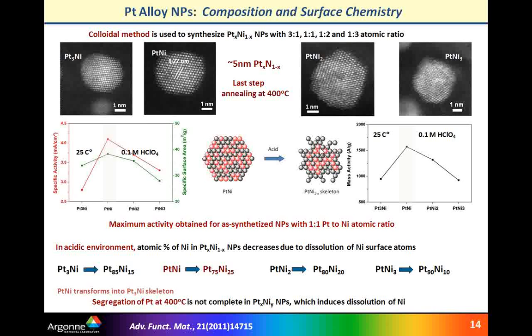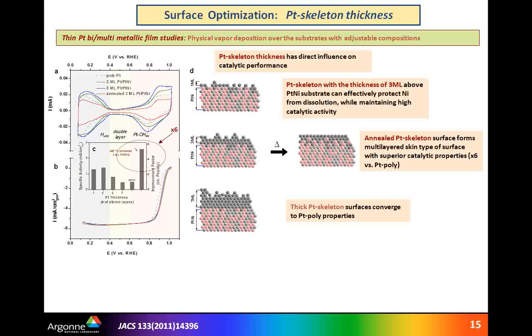However, nickel which is inside of the particle is still protected, and the amount of nickel in particles still stays at about 50%. So from there, we wanted to tackle in a more controlled way how we can further manipulate those surface properties. And therefore, we went back to our extended surfaces, and here we relied on a thin film approach. So not only were we able to vary and control bulk composition, we were also able to simulate different thickness of remaining platinum on the surface that we termed platinum skeleton. And here we varied the thickness of platinum skeleton from 1 all the way to 7 monolayers.